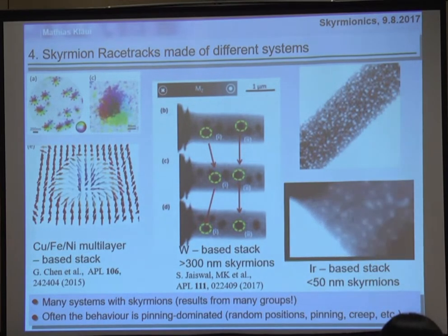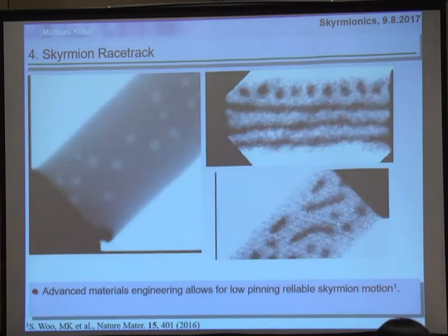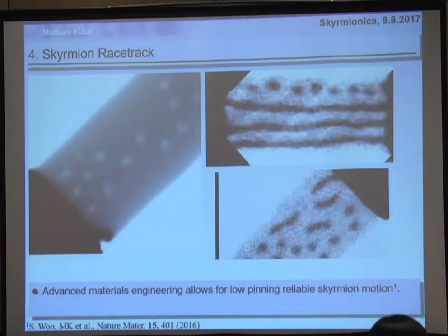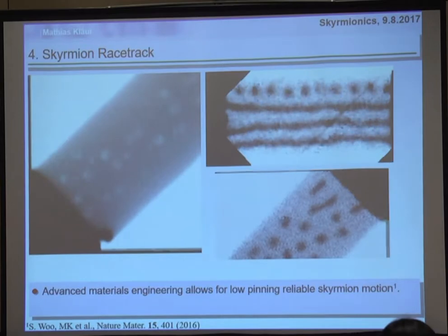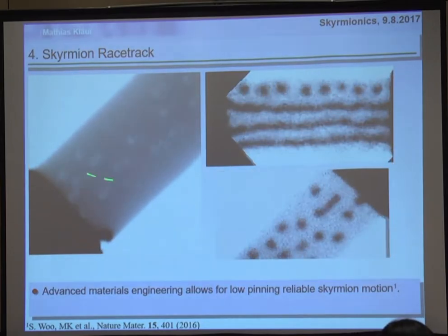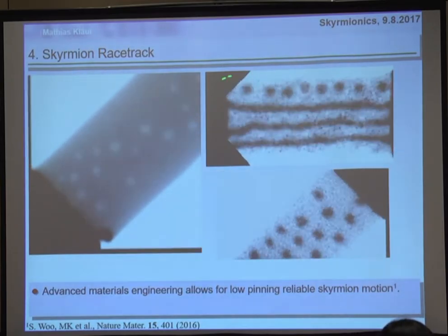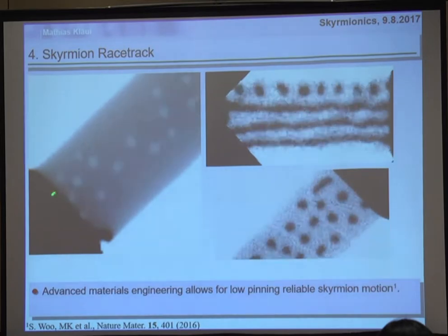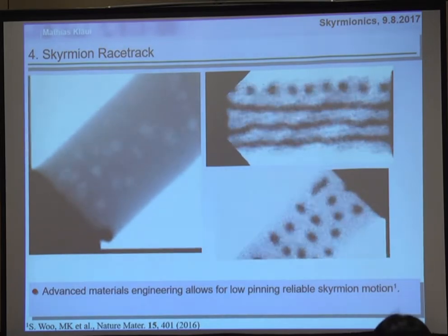Then we went out to change materials and change growth parameters, and after a lot of hard work, so this sounds very easy, but this was like 110 stacks later, we have a stack where we see that the skyrmions move at least 50 times back and forth very happily.